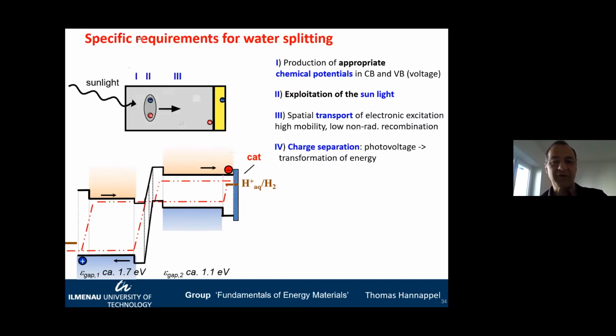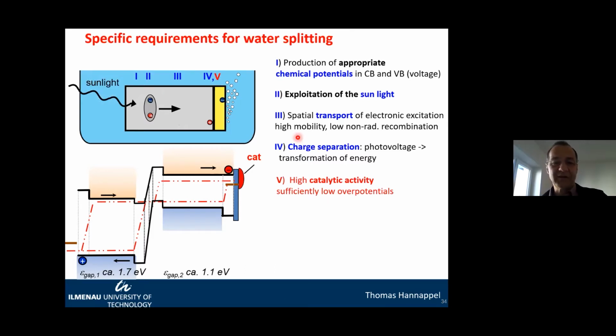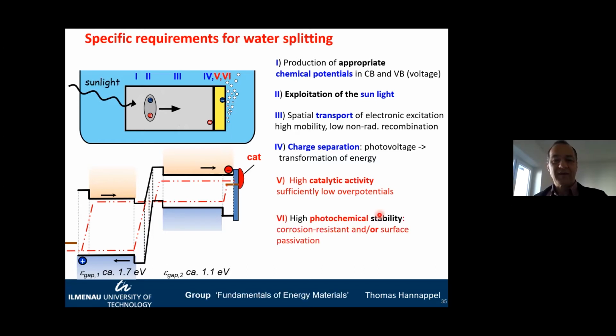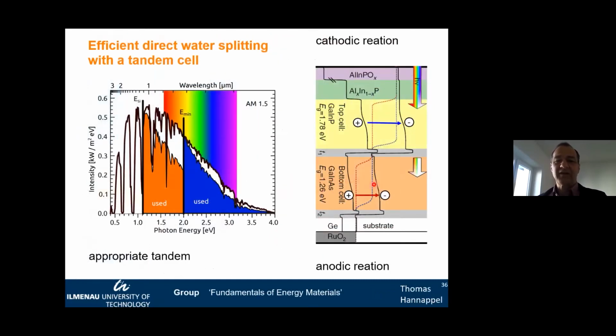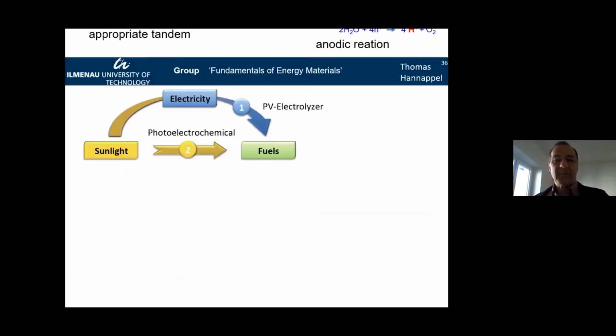And beyond this, of course, we need to study the catalytic activities. This is, of course, also a huge field which we need to work on. And besides this, of course, we need to work hard on the issue of stability, of corrosion, of the solid-liquid interface, of chemical passivation. And then you can see here a kind of perfect device structure which can be realized in this case by III-V semiconductors, where you can see the whole mechanism here for producing hydrogen and producing oxygen and exploiting the light very efficiently. Okay, that's what I wanted to show.